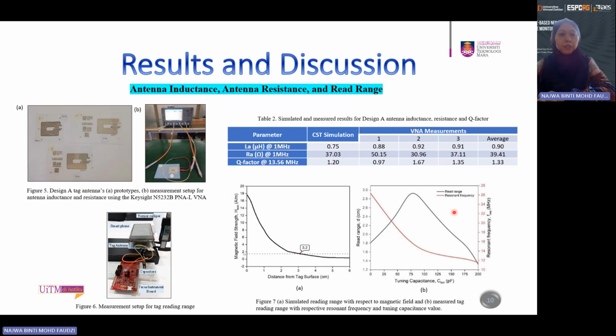The measurement of the tag reading range has also been conducted using this NFC-enabled smartphone. For example, here I'm using a Xiaomi 11T, and the distance between the reader and the tag has been measured by using a Vernier caliper. The measured and simulated results have been compared. From the simulation, the maximum tag reading range achieved is 3.2 centimeter, where the maximum distance was observed at 1.5 ampere per meter of magnetic field strength, which is the minimum strength required to power up the tag antenna.